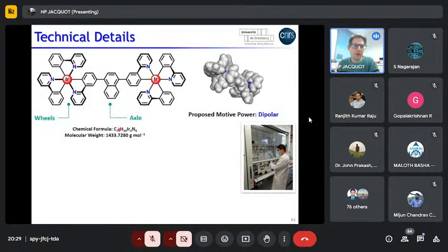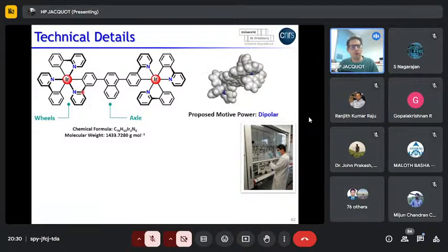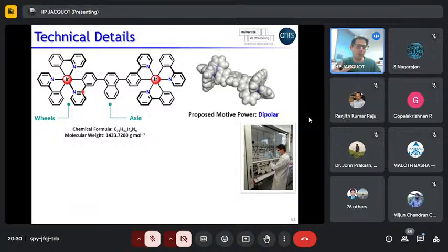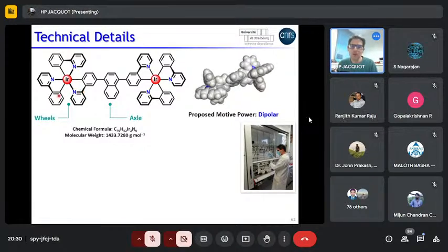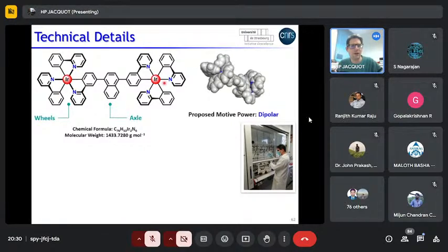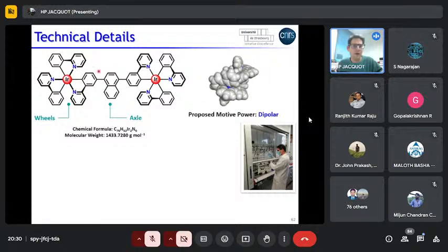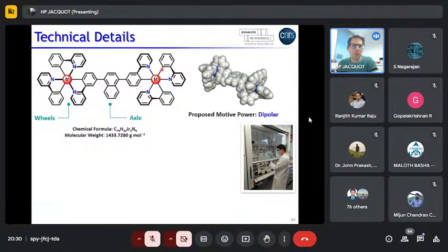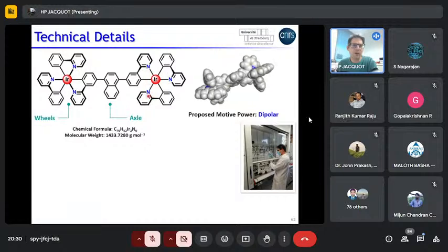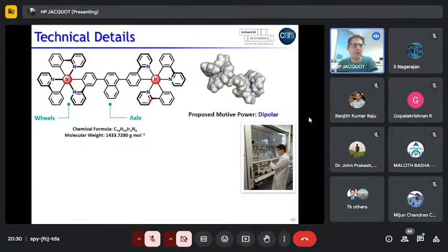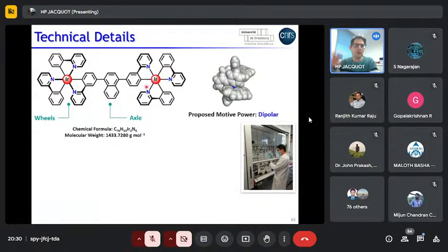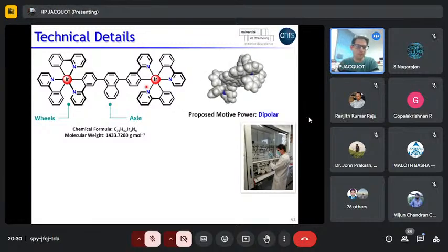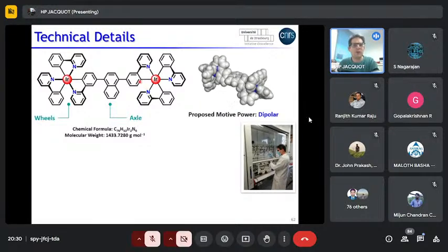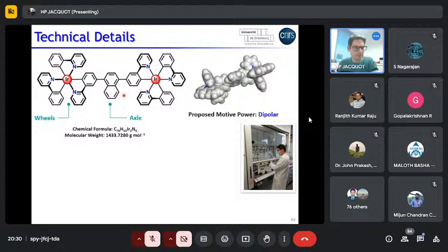So the molecule is very simple. What you need to do is to have a very small molecule, the minimum molecular weight to make it move fast on the surface. So that was a bis-iridium complex having an axle in between the two iridium centers. This molecule has a strong dipole moment because you have the fac isomers of the iridium complexes. So the three nitrogen atoms are facial, and then on the opposite side, you have three carbon atoms.